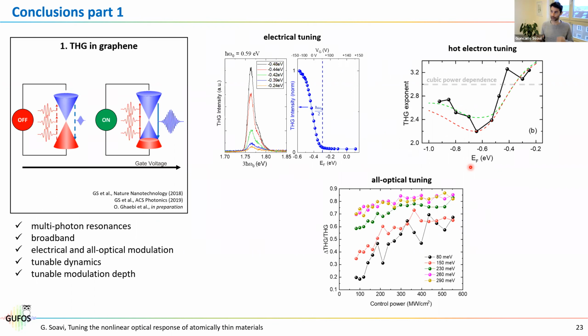So just to summarize the first part, we have been working quite heavily on this optical and electrical tuning of third harmonic generation in graphene, and graphene is indeed a very peculiar, very special material, because thanks to the linear dispersion, we can heavily change the third harmonic generation efficiency by applying a gate voltage, and by changing the Fermi level, we can move in and out from this multi-photon transition.